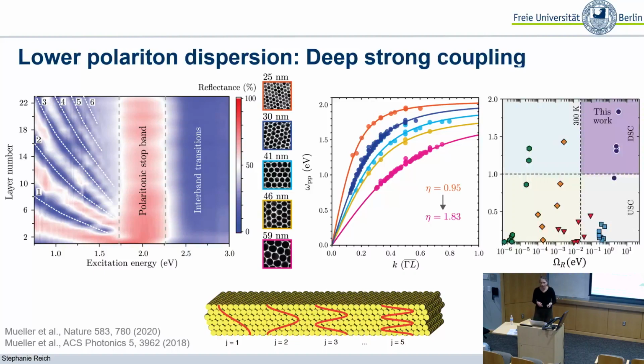And then here's one of these famous viewgraphs where you show what everybody else did and how much better you are than what they attempted. So this is the reduced coupling strength. Above 1, we have this regime of deep, strong light-matter coupling. And down here is the absolute coupling strength, so how large it is. You can see that we are the highest in reduced coupling strength, and we are also the highest in the absolute coupling strength, which is very important because it means we don't have to go down to cryogenic temperatures and so forth in order to observe these exotic states.